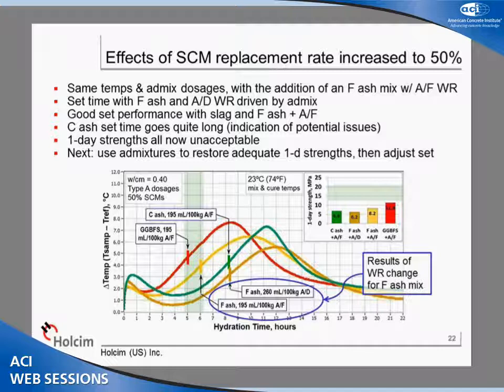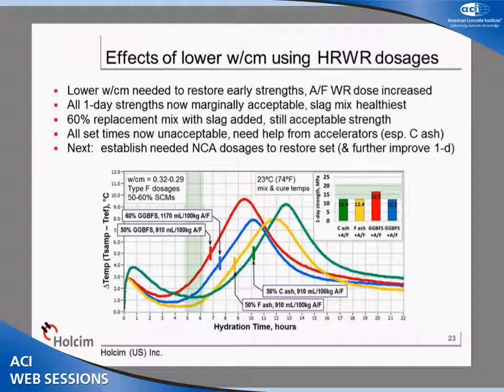But first, let's try to get our one-day strengths back in target. And to do that, we're going to need to lower water cementitious ratio. Chemical admixtures are obviously the tool that we need for doing that. So if we increase the dosage rate of the chemical admixtures and lower the water cementitious ratio, in this case generally from 0.4 down to about 0.32, then now we have a set of one-day strengths that are beginning to bump our target band. Okay, we'll actually improve those a little further with the use of some accelerators later on. But this, for argument purposes, this gets us in the zone.